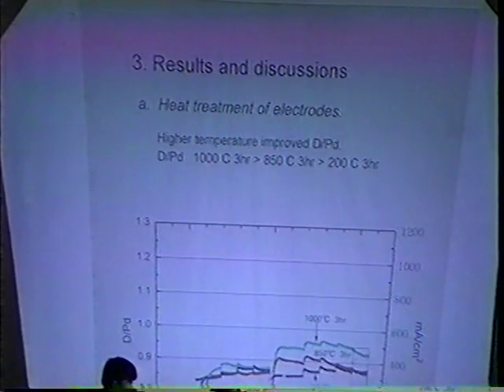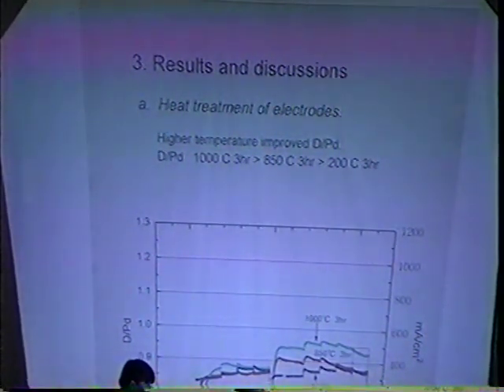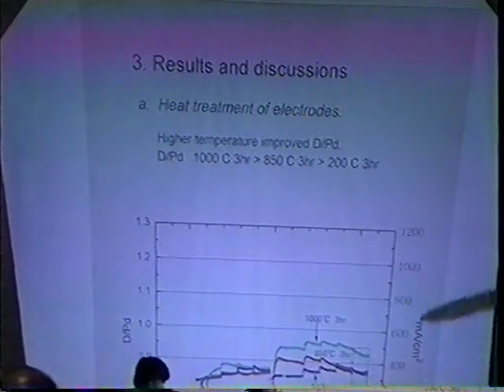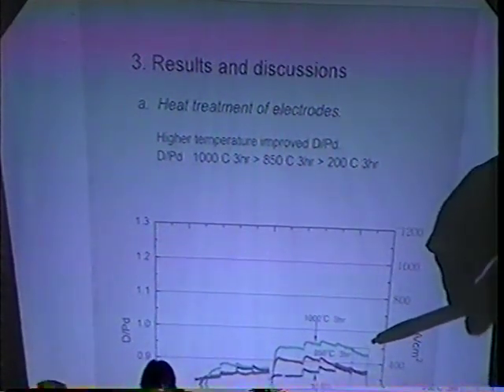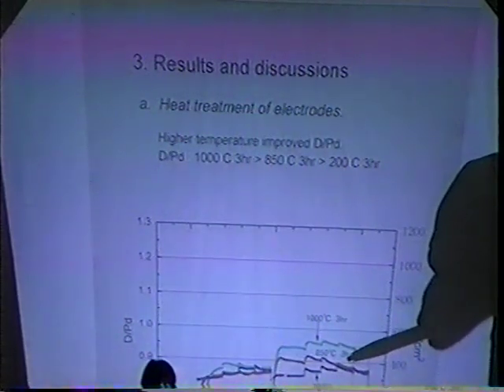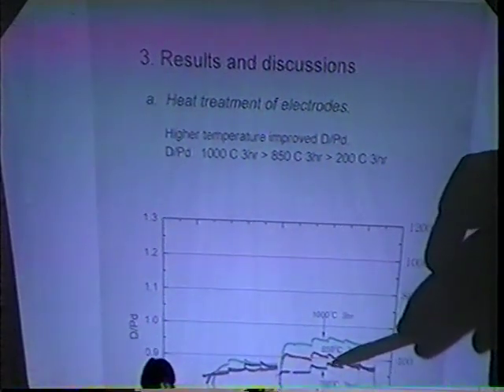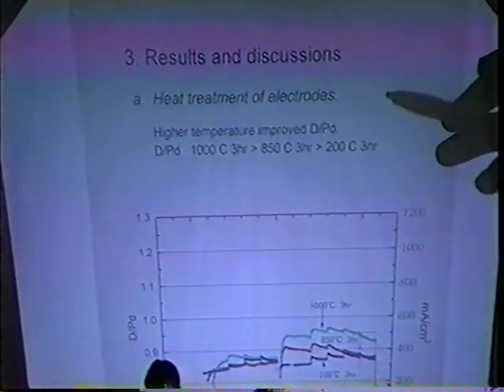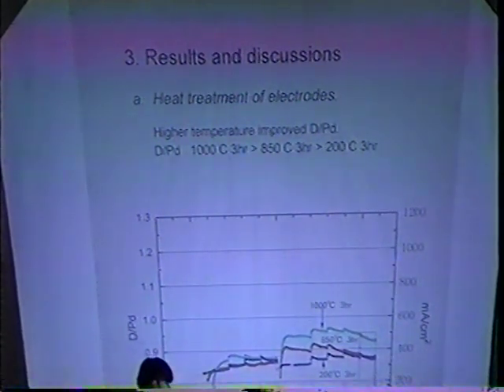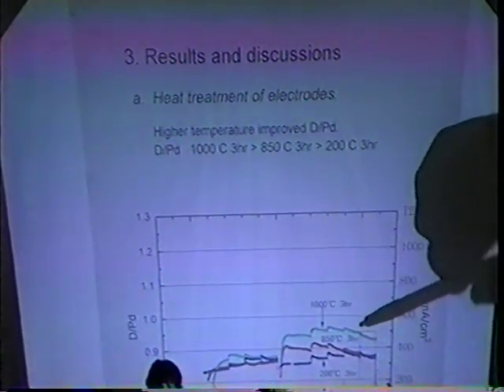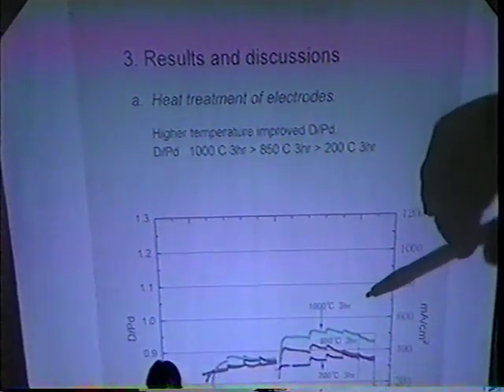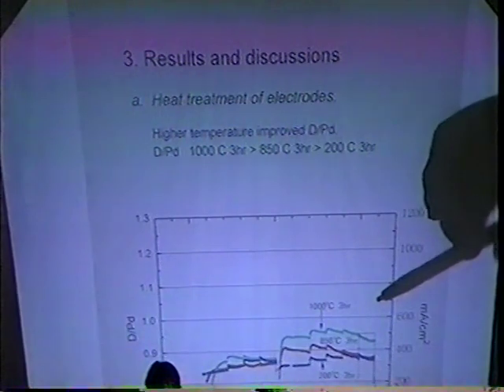This graph shows typical results comparing the effect of different annealing temperatures. The green line corresponds to a sample annealed at 1000 degrees C. The red line corresponds to 850 degrees C. And the blue line corresponds to 200 degrees C. The best results were obtained for the sample annealed at 1000 degrees C, indicating that electrodes heat treated at higher temperature probably yield a higher ratio.